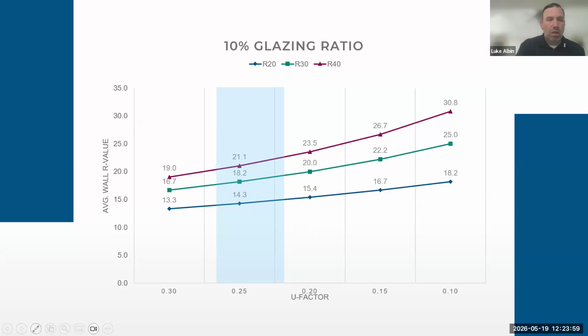How do these windows, when we put them in, affect the overall wall assemblies? I know we're always trying to strive to get to a certain window to wall ratio. Well, as we take a look here, this chart will show the average wall value, and then on the horizontal axis, you've got the window U factor. So we're starting off at 0.3, and as you move from left to right, you get a better performing window. So this is a 10% glazed area. So you'll see an R20 wall, R30 wall, and an R40 wall.